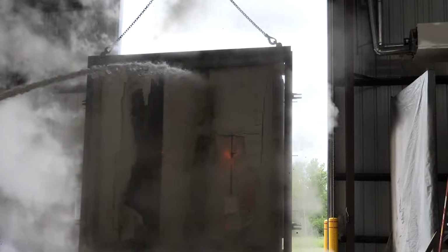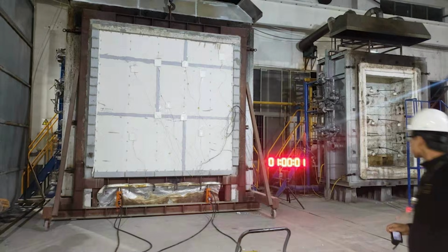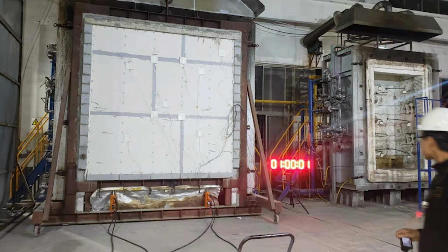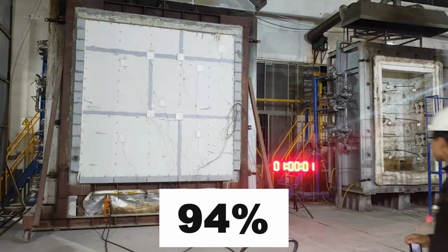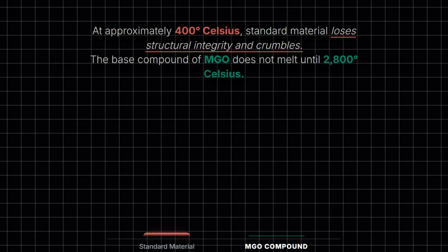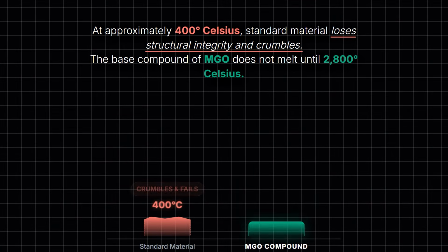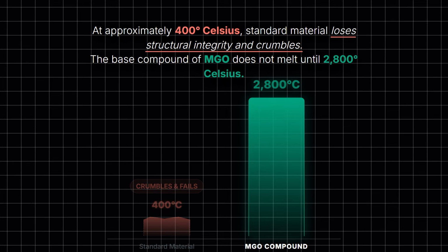When the furnace opened, the panels had charred on the surface. The structure was intact. Fire hoses applied to the superheated wall produced no water penetration. Structural strength retained, 94%. By comparison, Type X gypsum drywall, the fire-rated product standard in American construction, carries a maximum 1-hour rating. At approximately 400 degrees Celsius, it loses structural integrity and crumbles. The base compound of MgO does not melt until 2,800 degrees Celsius.